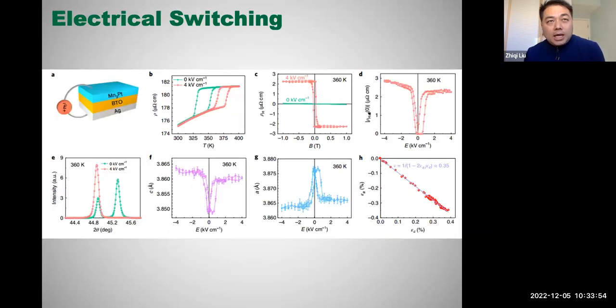Similarly, we use an electric field to generate a piezoelectric strain via the barium titanate. The piezoelectric strain can modulate the phase transition temperature. Around its phase transition temperature, the two antiferromagnetic spin structures could be turned on and off by the piezoelectric strain or electric field. In this way, we could turn on or turn off the anomalous Hall effect.